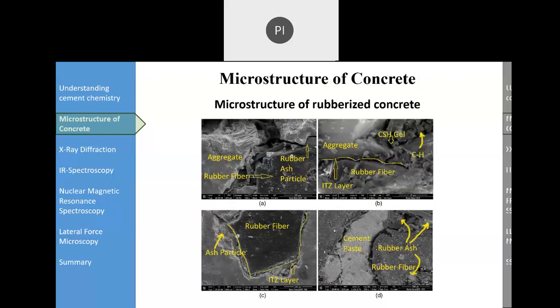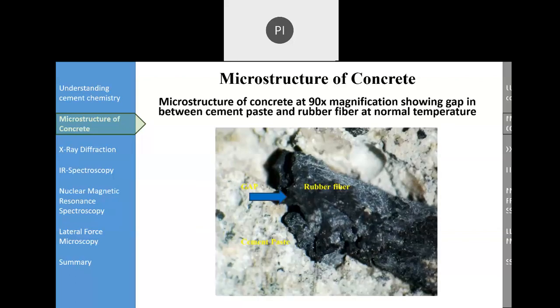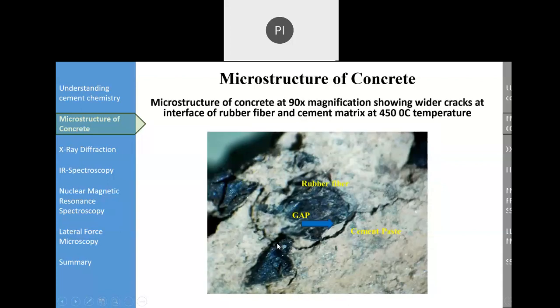So what is important is we need to understand that we need to go through these microstructure images, and then that can give us a lot of information. Like you can see when we did another study on the temperature also, here you can see the rubber fiber, and there's initially some gap between the rubber fiber and cement paste, and then we increase the temperature, so the gap between the rubber fiber and cement paste is increasing.